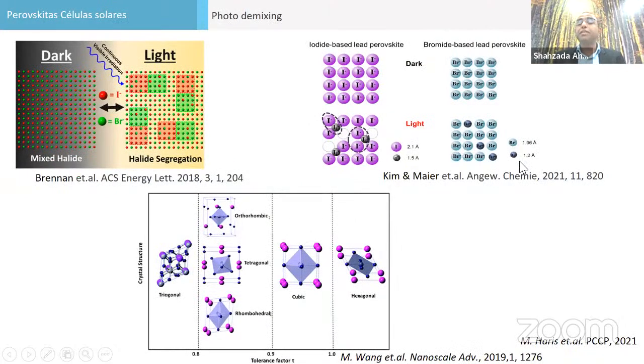As I said about the mixed perovskite, everybody was very happy, but we saw that when we put light, they are very mixed, but when they come in the dark, they are good. Under light, sometimes there is mixing and demixing of the halide, and they form clusters of halide, bromide together, and there is sometimes phase separation, and it's not good. A very good article was also published by some people. They found with different techniques how the phase separation is occurring and how they are sticking together.